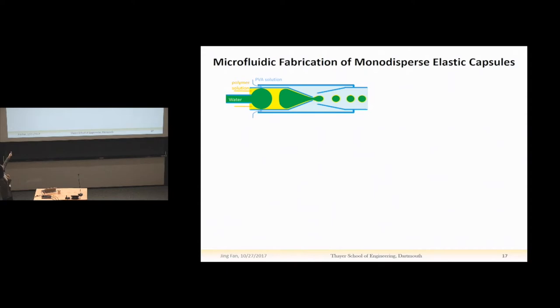This very small capillary is used to inject the inner phase, which is an aqueous solution of the surfactant in this case. And the middle phase, entering from here between this small capillary and this larger round capillary, is a polymer solution in an organic solvent. This polymer will actually become the shell material of the capsules. And the outer phase is another aqueous solution with surfactant. So the inner phase is broken into some large liquid slugs at this junction. And each of these